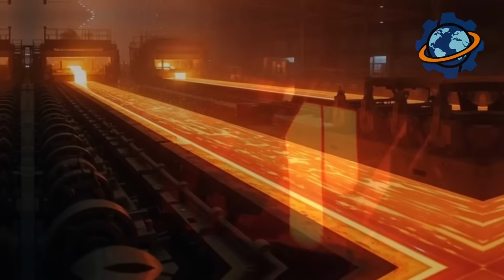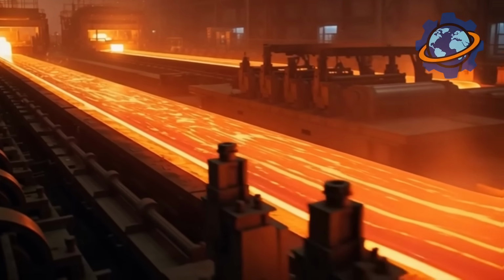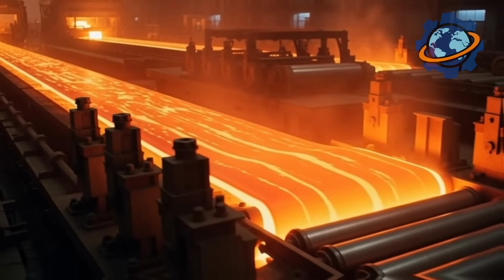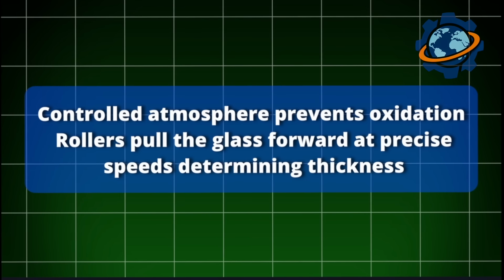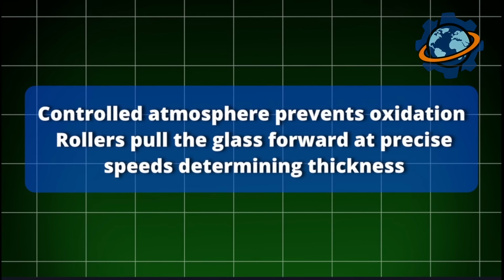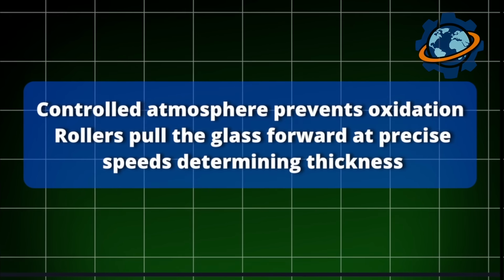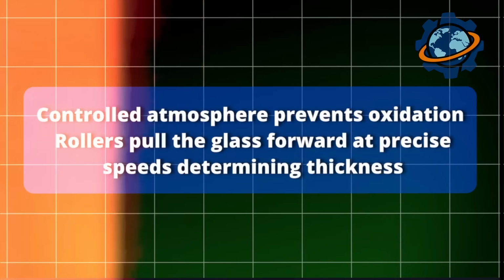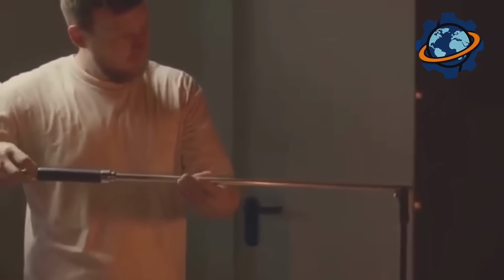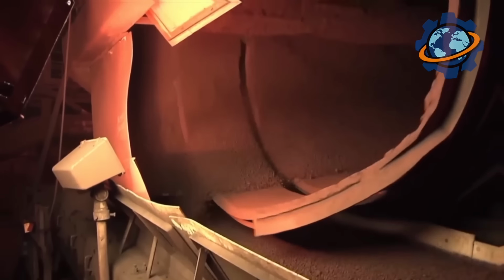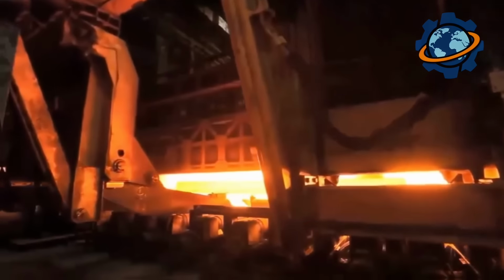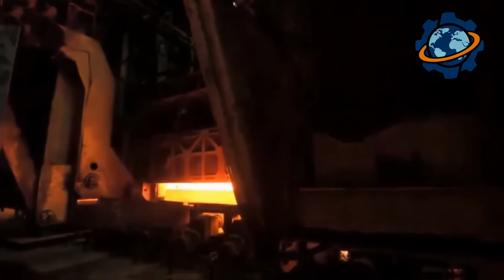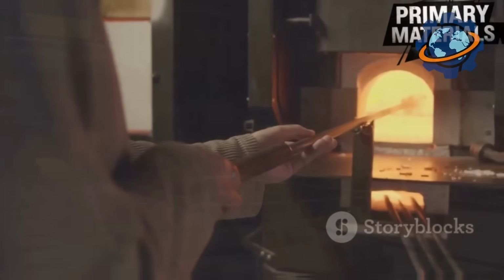Watch the float bath. The glass ribbon, still glowing red, stretches 300 feet across the tin. Controlled atmosphere prevents oxidation. Rollers pull the glass forward at precise speeds, determining thickness. For automotive glass, thickness reaches 0.18 inches for windshields, slightly thinner for side windows. The glass gradually cools as it travels, solidifying while maintaining molecular randomness. No crystals, no grain structure, pure frozen liquid.